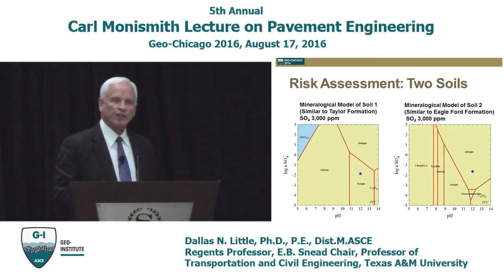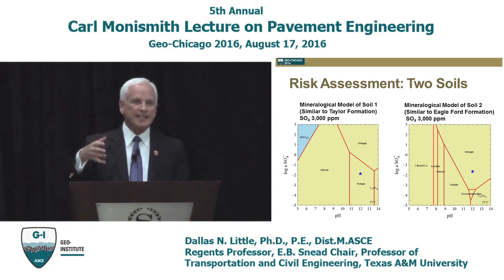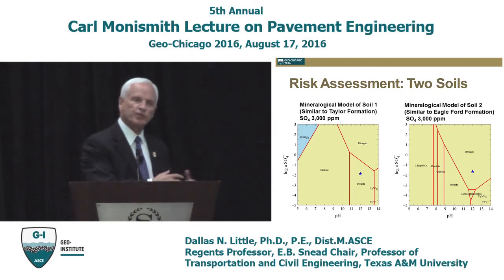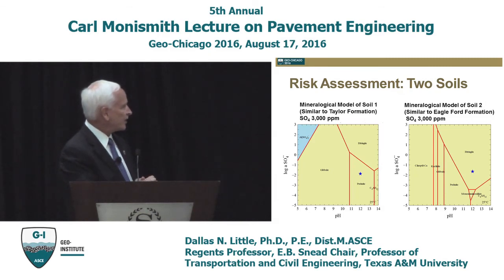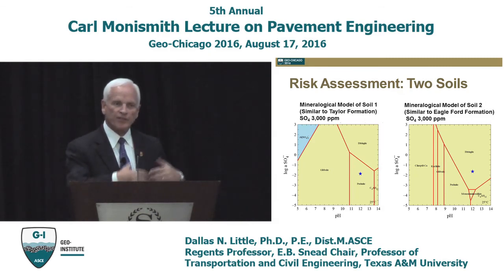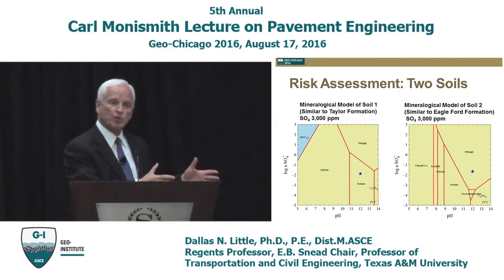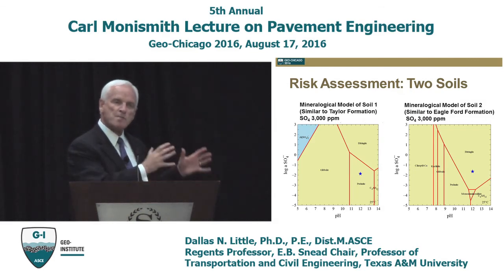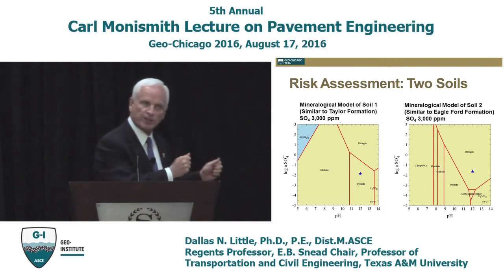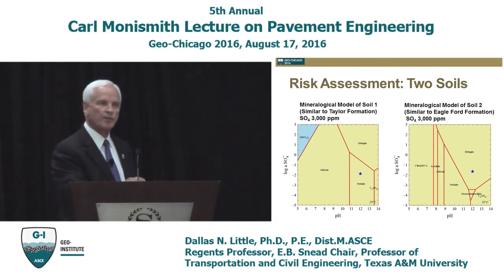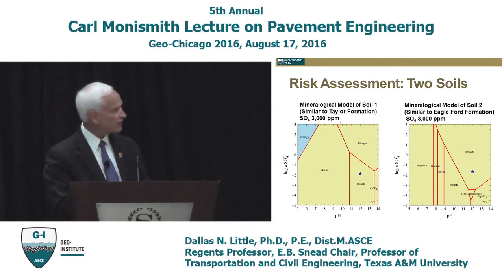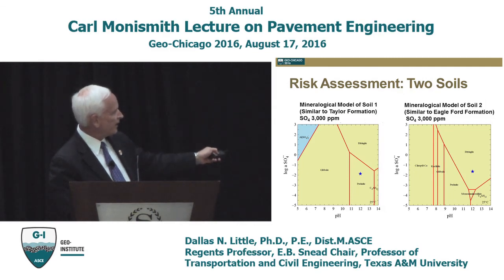So the first step that we did was we went back to the Gibbs free energy principle, and we looked to our geochemist. And our geochemist said, well, you can do something called a phase diagram, which allows you to evaluate for a particular mineral, if you can really identify what's in that mineral, whether ettringite is thermodynamically stable in that environment. And that's exactly what you see in these 2 diagrams. Probably hard to see at the back of the room, but this polygon right out here is ettringite.